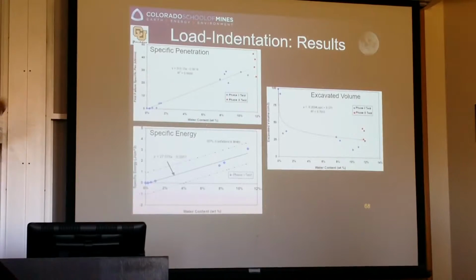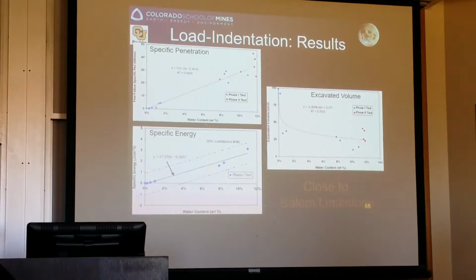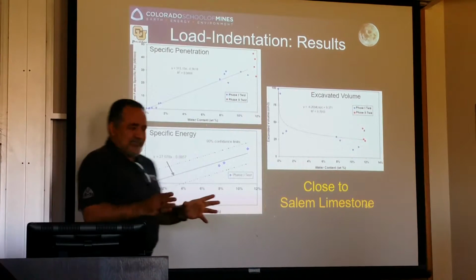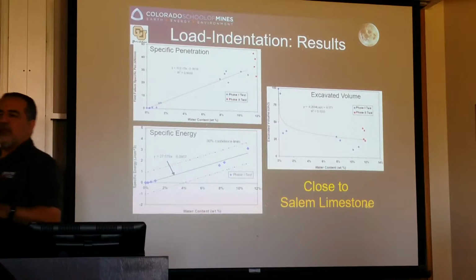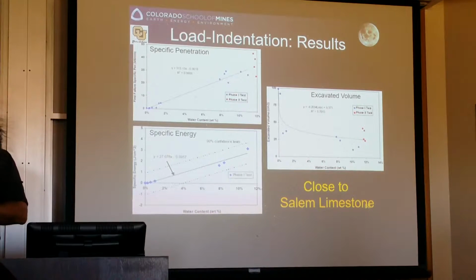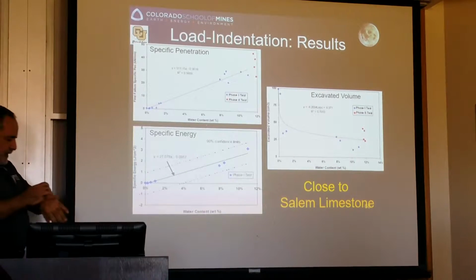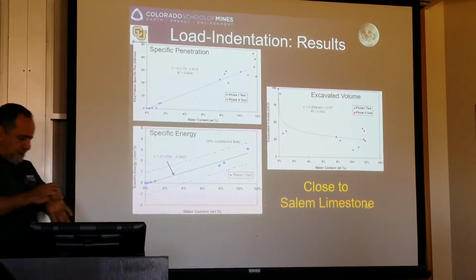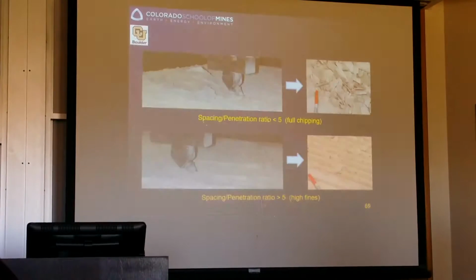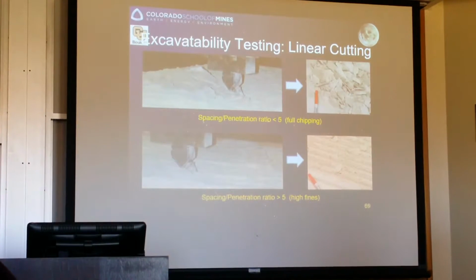So looking at all this test data and whatnot, we concluded that an analogous to a frozen regolith could be this Salem Limestone. So for all the tests in room temperature, we actually use the same Salem Limestone, okay? So what did we do? We actually took a block of Salem Limestone that was about 5 feet wide, 6 feet long, 2 feet high. We started cutting it.